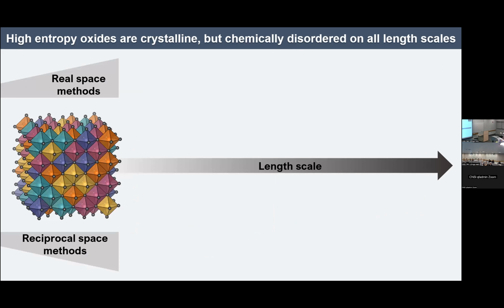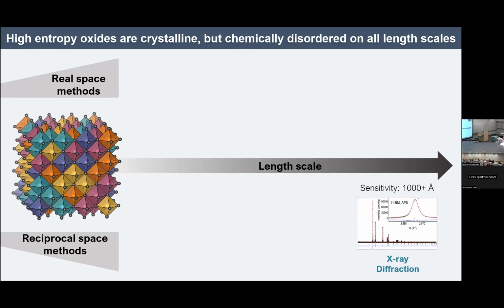Okay, so this is our canonical picture for a high entropy oxide. It's a rock salt structure where the oxygen atoms are confined to a completely ordered sublattice, and it's only the cation sublattice that is disordered. I would argue that it's quite a beautiful picture, but it's not entirely clear that such a thing should be real or should exist. To validate the existence of such a material, we can look at a number of different probes along many different length scales and in both real and reciprocal space. One requirement is that they should be crystalline, meaning that on average they obey translational symmetry, that we can describe their structures with the language of space groups, and that in a diffraction experiment we should measure sharp resolution limited peaks, and that's indeed what is found.